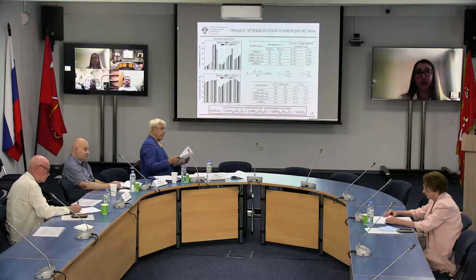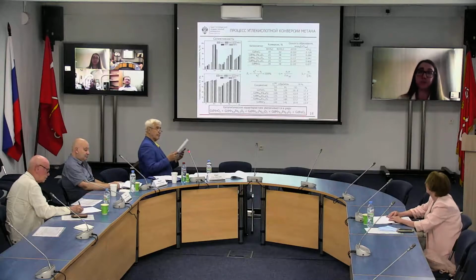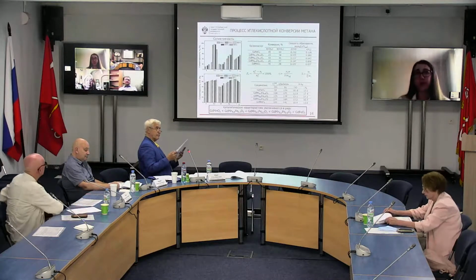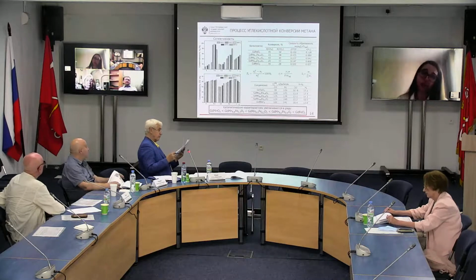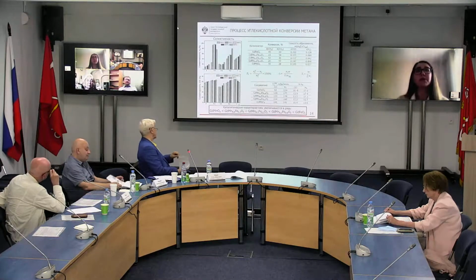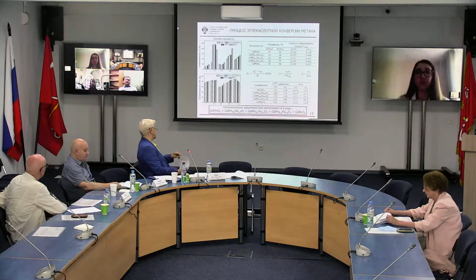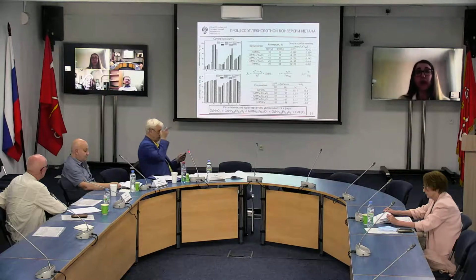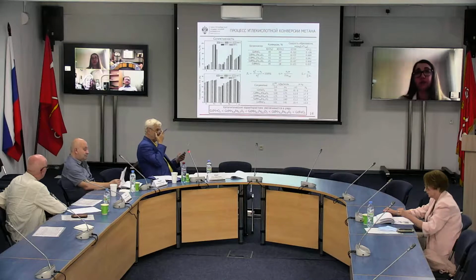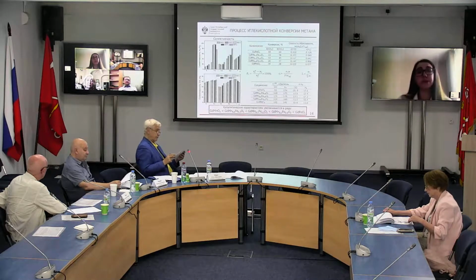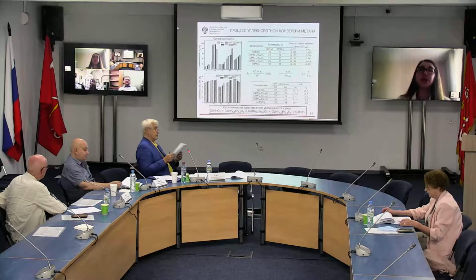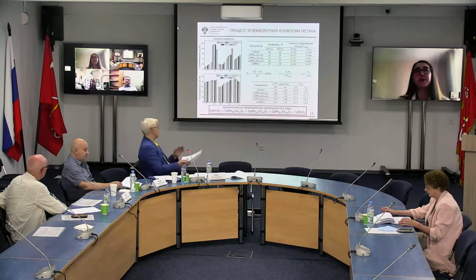Dry reforming of methane, a reaction with manganese-containing perovskite-like oxides, showed that when there is a rise of manganese in solid solutions, we see a drop of catalytic activity. And for samples with non-stoichiometrically substituted ferrum with manganese, we see a growth of selectiveness for hydrogen, and selectiveness values for this type of gadolinium with manganese, ferrum 0 and 0.3, reached 80%.